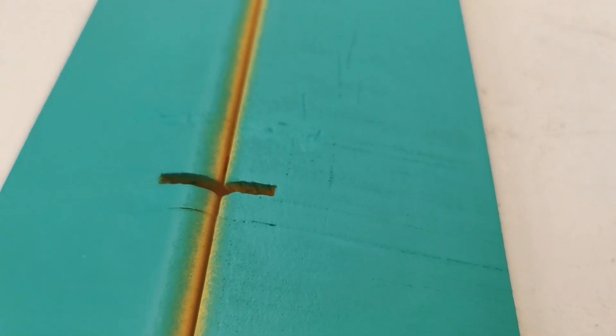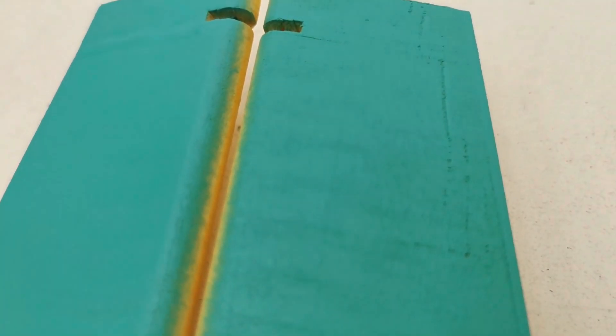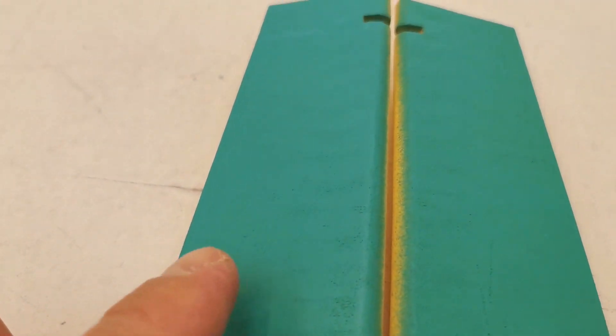It's a little bit different but I think there is a difference. Here are also pinholes but not that much. I think this is caused by the shrinking afterwards while curing of the varnish. So the surface is not that good as with the resin. I think this surface is better, just a bit better but it is better.